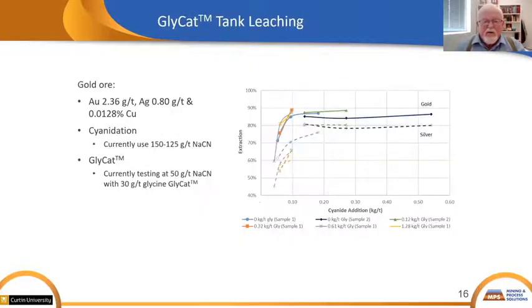Now, here's a rather complex graph, and this is tank leaching with two domains from the same mine. And note the solid colored curves represent gold extraction, while silver is represented by the dashed curves. And all experiments have a common time period of 24 hours. Vertical axis in the graph is recovery. Horizontal axis is cyanide use in kilograms per ton. And you'll notice that we're working in the region from 0.3 of a kilo per ton down to around 1/10.